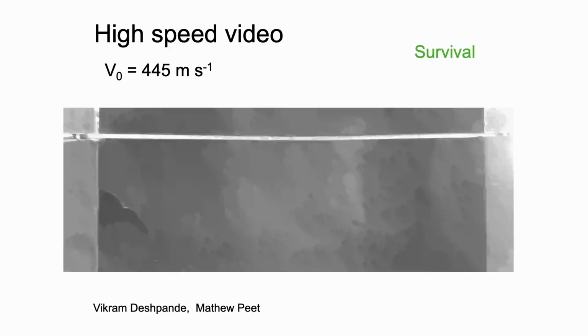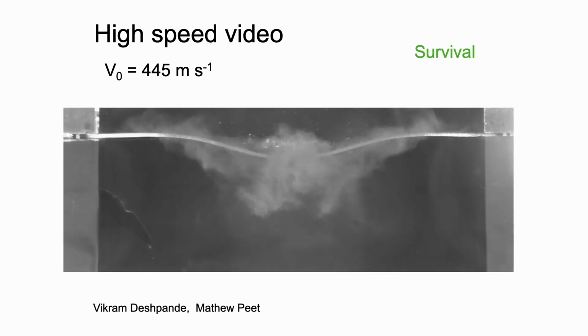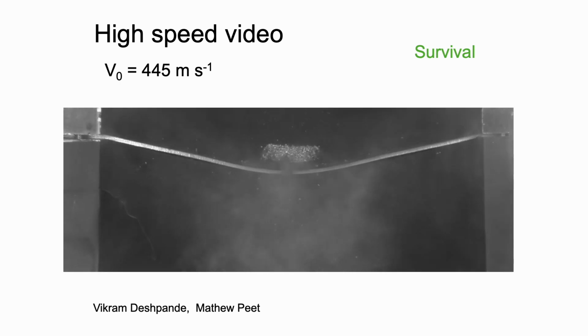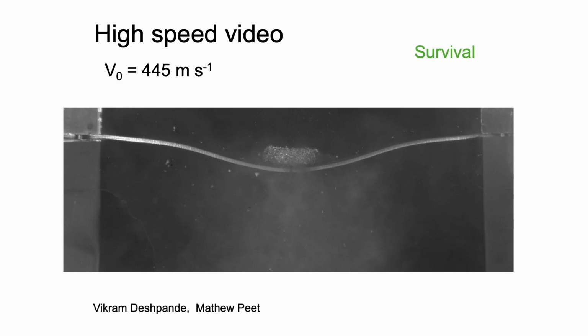This is a test to simulate a blast. A blast is a sudden distributed load, and in the university we would test that by firing aluminium foam at high speed onto our steel, which is clamped at both ends, and of course the steel must not fracture, and also it must not bulge too much, because if you're making a vehicle using this for it to be blast resistant, you know, obviously it can't bulge too much into the interior of the compartments where people are. So just imagine, in this very high strain rate test, the material of untempered martensite survives, okay?